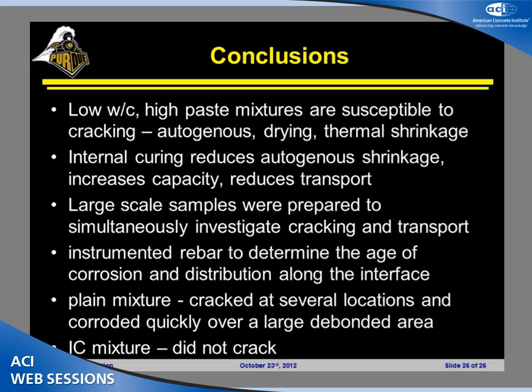Well, okay, so there are a few ways to go. When we talk about what is optimal, what I would say here is we can use a wide variety of internal curing agents to get what we want to get. We have found success in using a wide variety of lightweight aggregates, expanded lightweight aggregates. As I mentioned, we tested all of them. The difference is you use a slightly different proportion of the aggregate based on absorption capacity. You may originally think that a low absorption aggregate is not as good in that case, but that doesn't really bear out because what you end up doing is using a little bit more of it, but it's better distributed throughout the system.